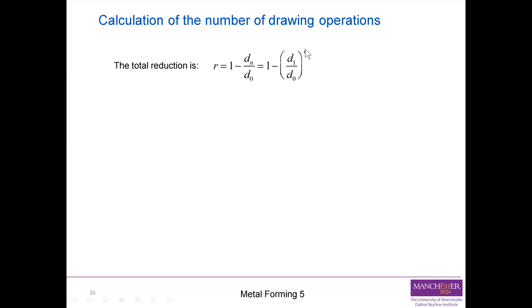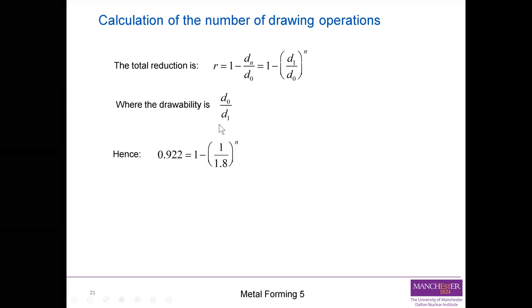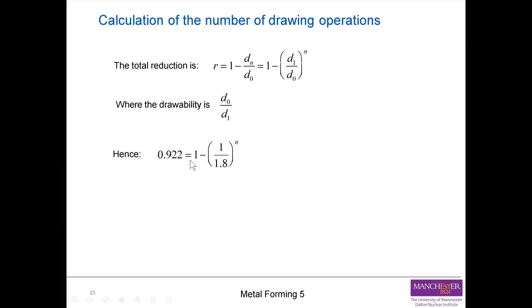if the number of operations is n, and the ratio is the same for each and every one of them, then we get 1 minus D1 over D0, to the power of n. And then drawability is D0 over D1. So if we substitute all the numbers we saw in the previous slides, we have 0.922 equals 1 minus 1 over 1.8, to the power of n. If we solve for n, we end up having n equal to 4.34.